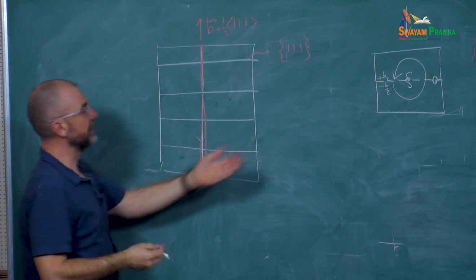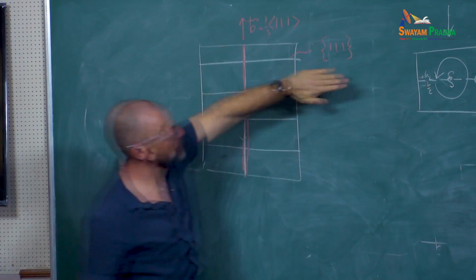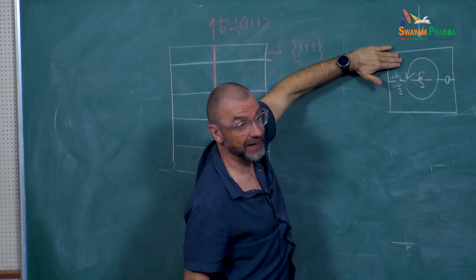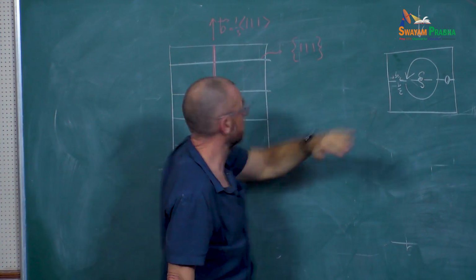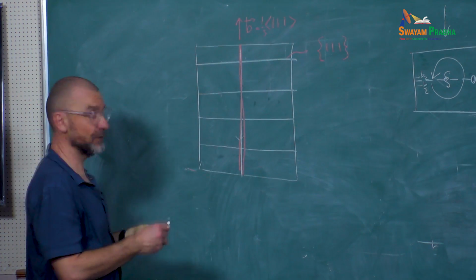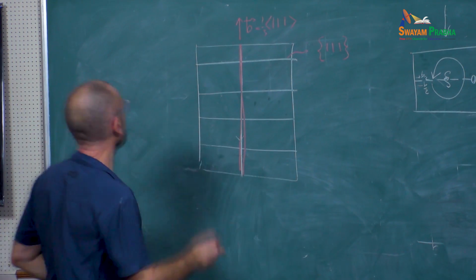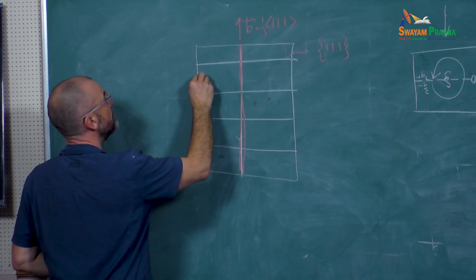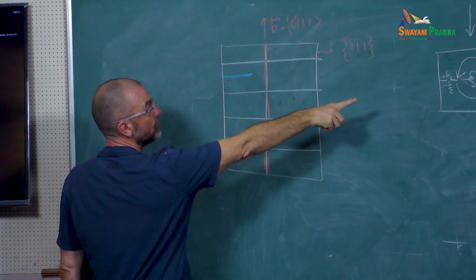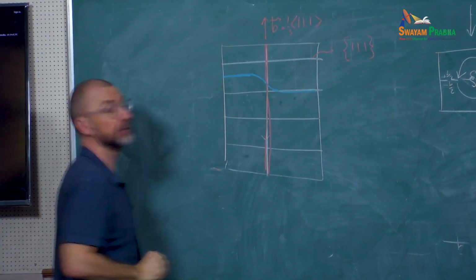Now if I'm looking behind, at the top part of the plane behind, what happens to that plane? It's going to be shifted by b over 2. So it's going to be somewhere here, right? And as I go towards the core, it's going to go to 0 like this.